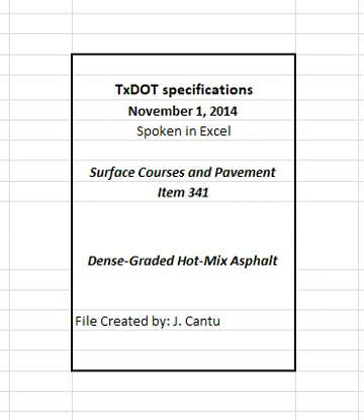4.7.1 Weather conditions. 4.7.1.1 When using a thermal imaging system, the contractor may pave any time the roadway is dry and the roadway surface temperature is at least 32 degrees Fahrenheit. However, the engineer may restrict the contractor from paving surface mixtures if the ambient temperature is likely to drop below 32 degrees Fahrenheit within 12 hr of paving.